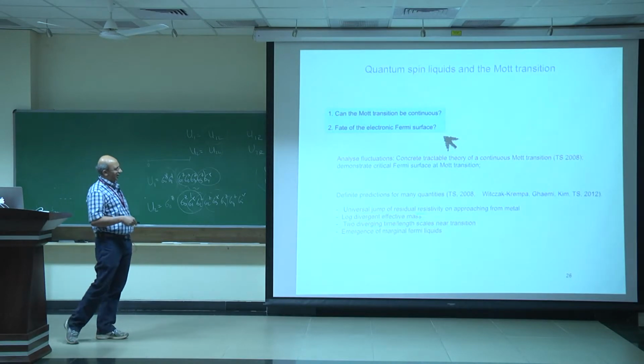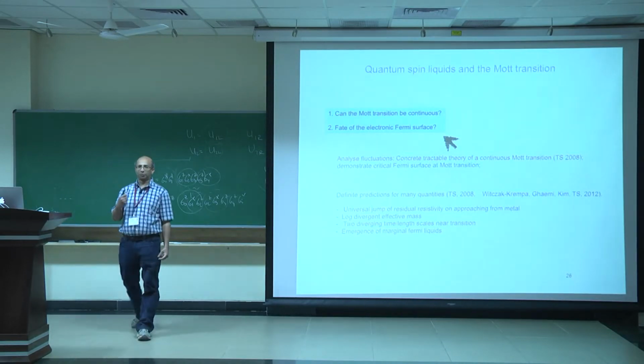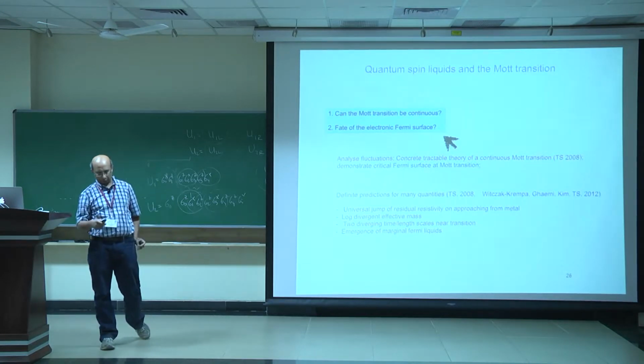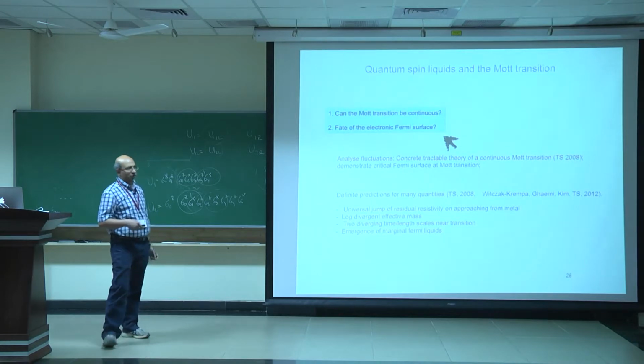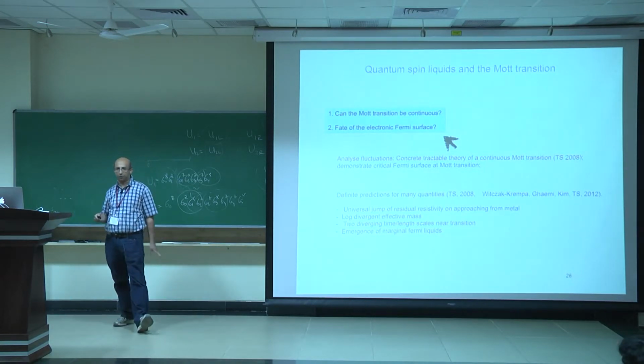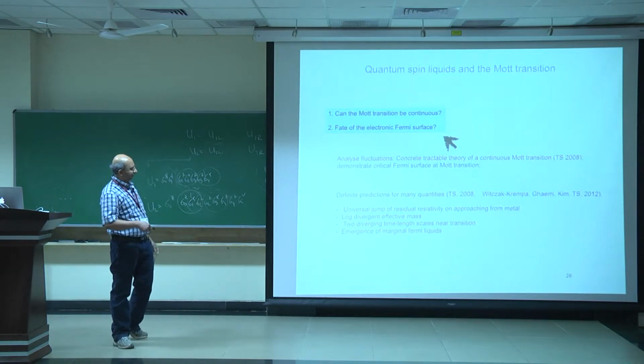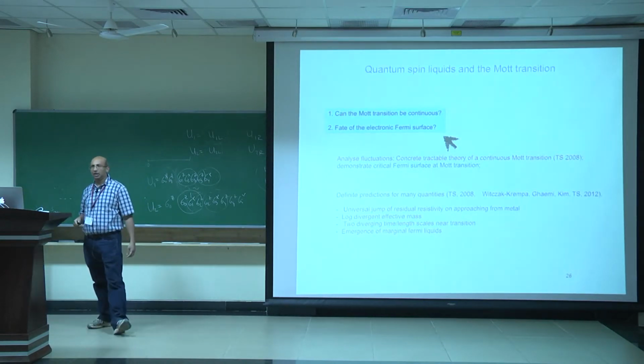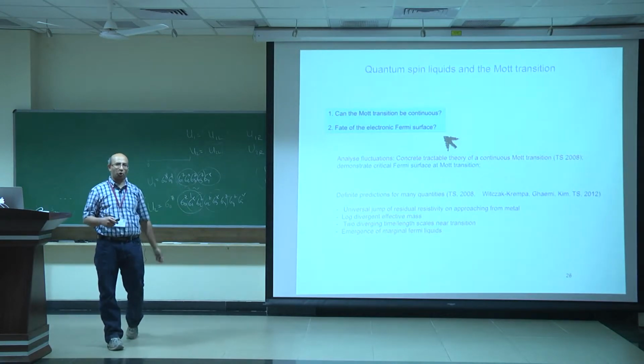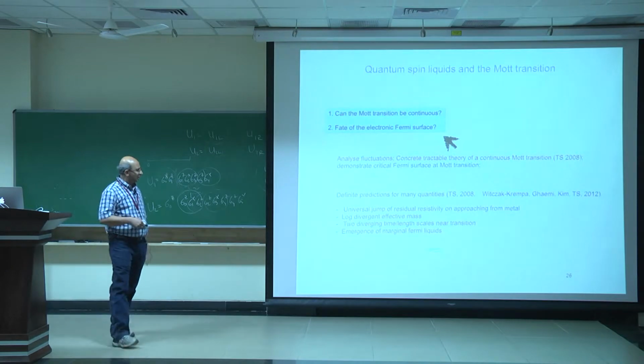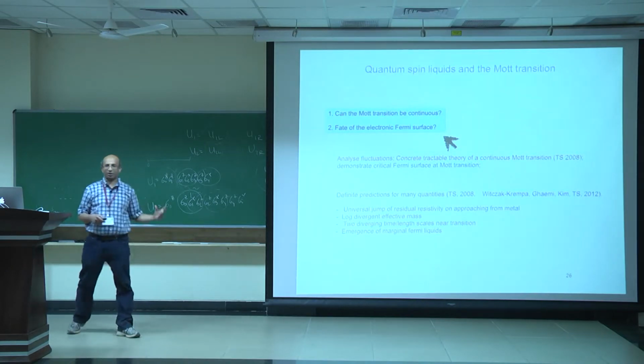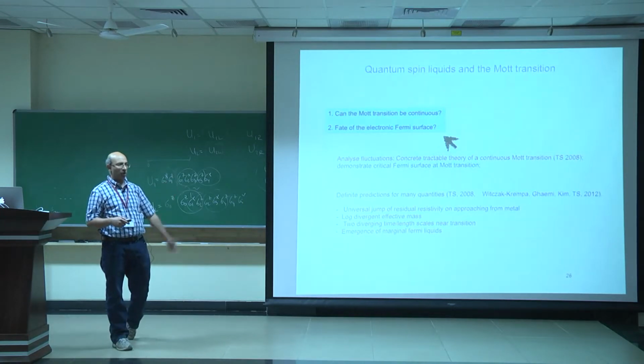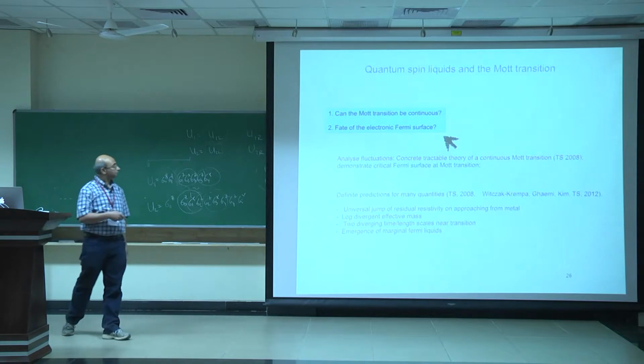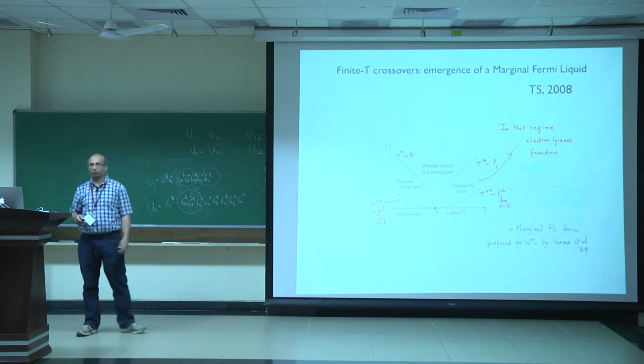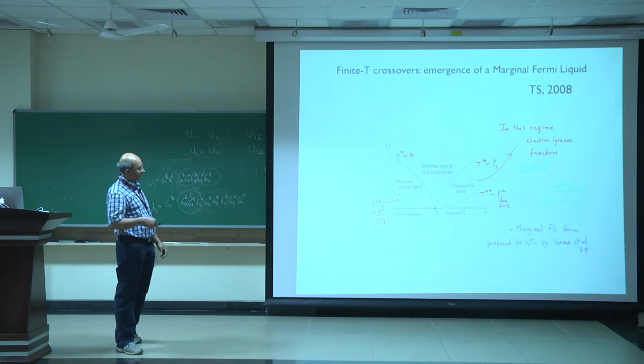A third prediction is that unlike a usual kind of quantum phase transition, there's more than one diverging time or length scale at this Mott transition. There are two diverging time or length scales, one associated with charge fluctuations, the other associated with spin fluctuations. Okay? And finally, at the intermediate length scale between these two length scales, or intermediate time scale between these two diverging time scales, there's an emergence of a kind of state that had been postulated phenomenologically for a number of years, known as the marginal Fermi liquid. That state emerges very naturally as a description of the intermediate scale physics near this Mott transition. Okay? So the picture of the finite temperature crossovers near this continuous Mott transition looks like this.